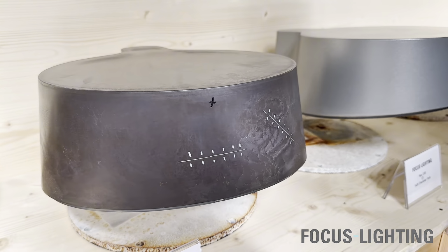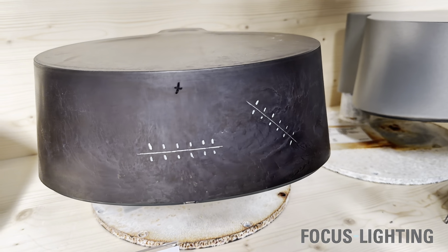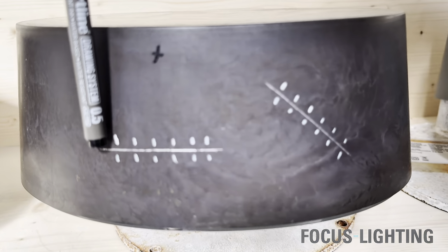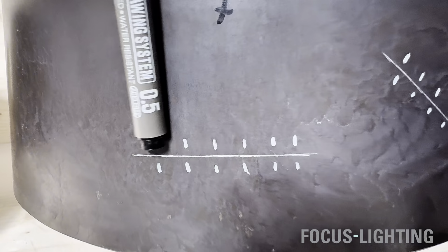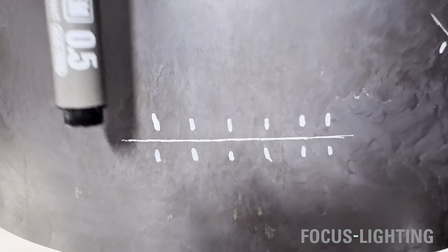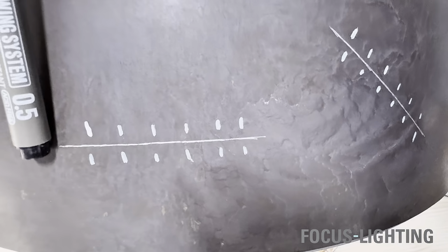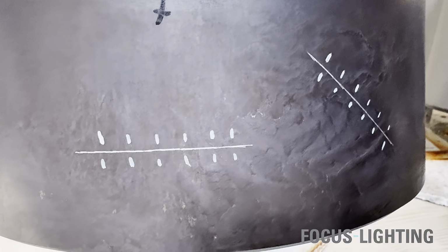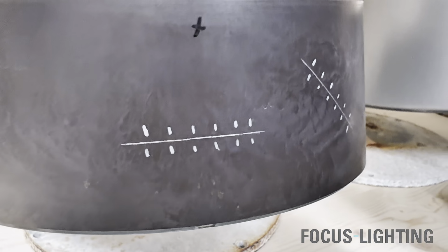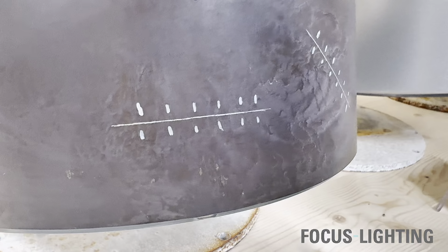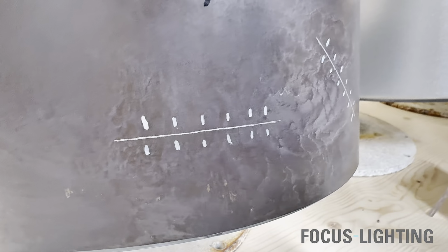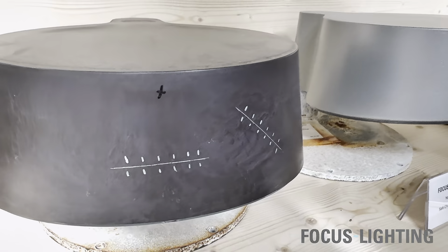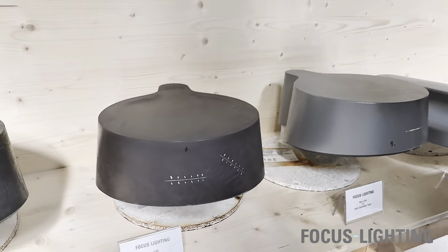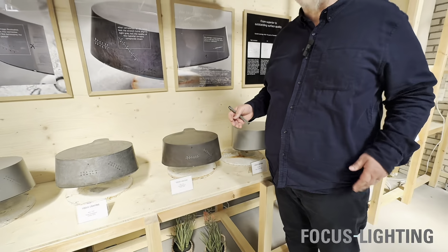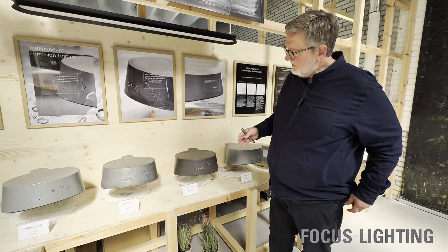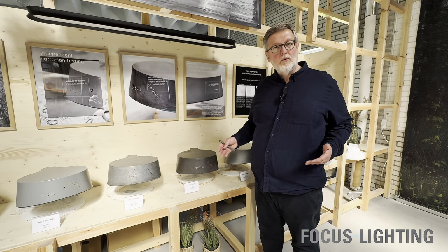Turning our attention to the corrosion protection, you see again the scratch. It turns light grayish, but there's no damaging, no corrosion to the housing at all. We cannot qualify this as C4 or C5 because these tests relate only to painted surfaces, and anodization is not painted. So we can't compare that to the standards of C4 and C5.